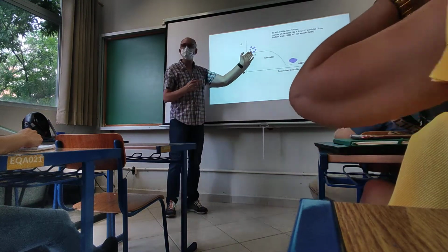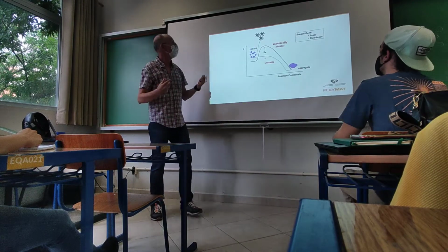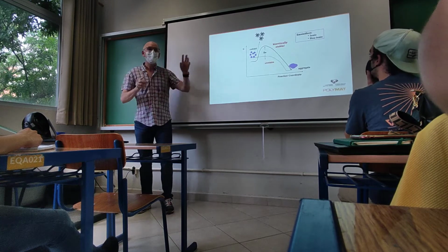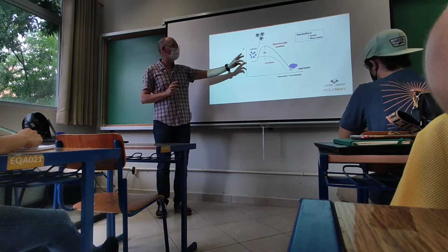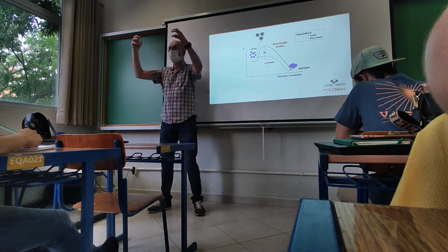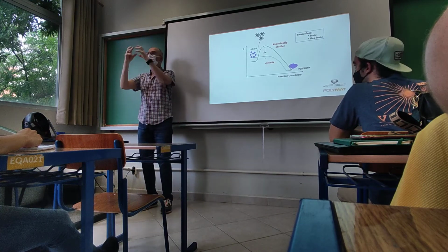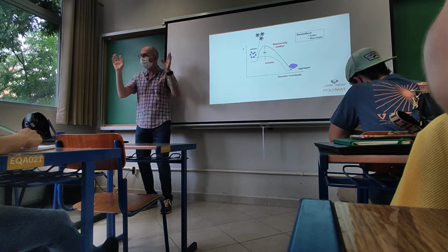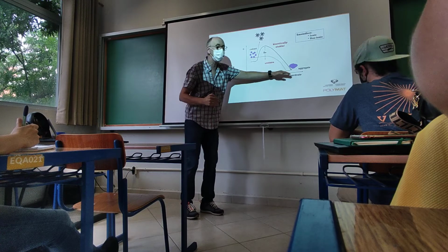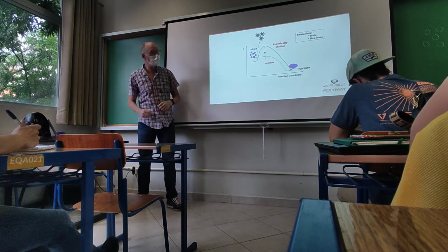So to maintain this stable, we need to have something on the surface of these particles. And this is what we mentioned, that we have surfactants. The role of the surfactants is to stabilize the polymer particles. Okay? So in another way, to create a barrier to avoid that upon Brownian motion the particles aggregate, so that we maintain particles kinetically stable, not thermodynamically, but at least kinetically stable. To avoid this aggregation, we create a barrier here that maintains the particles stable in the atmosphere.